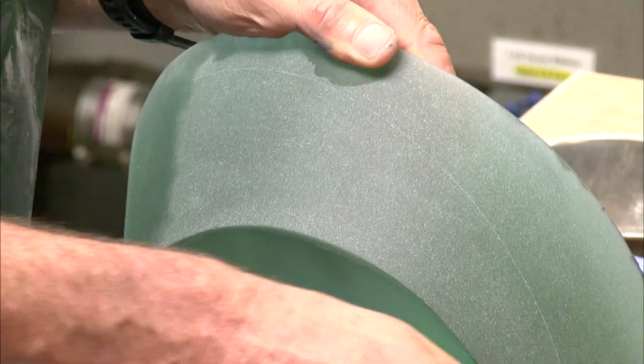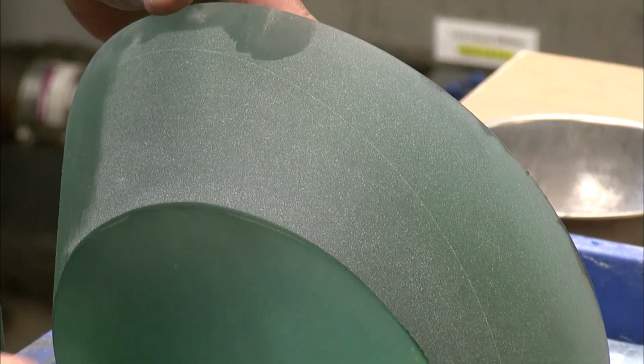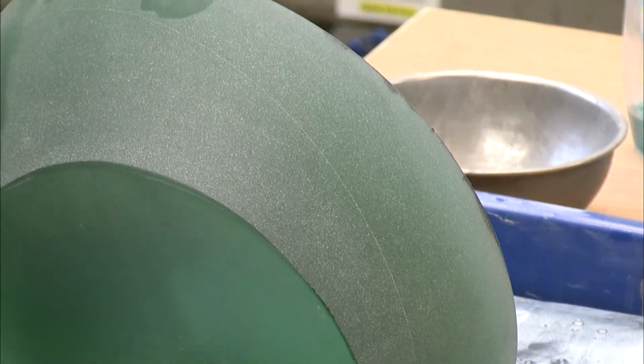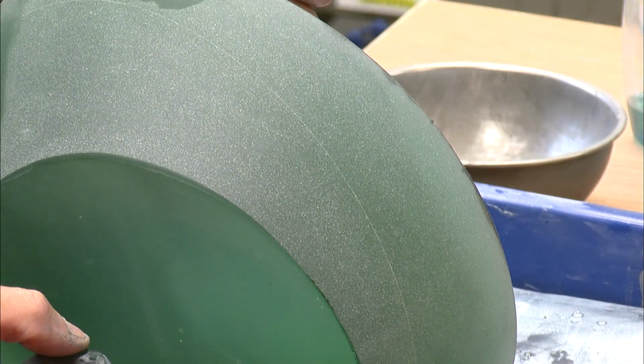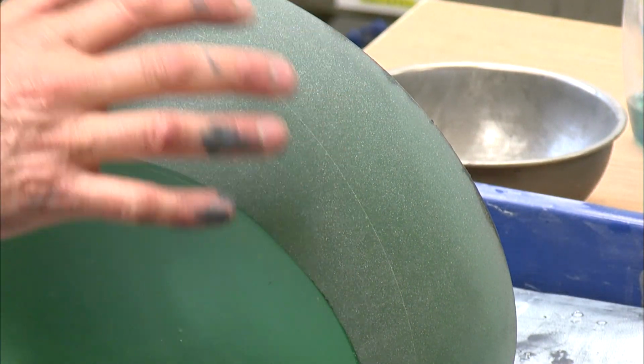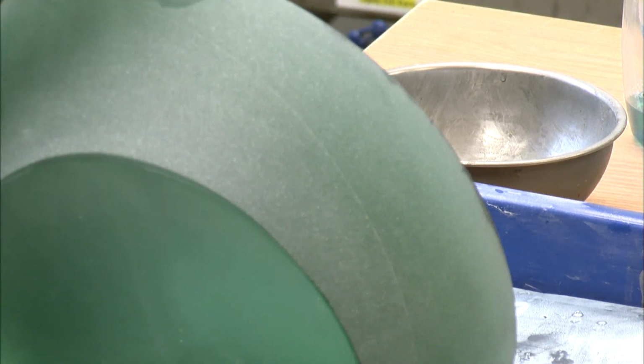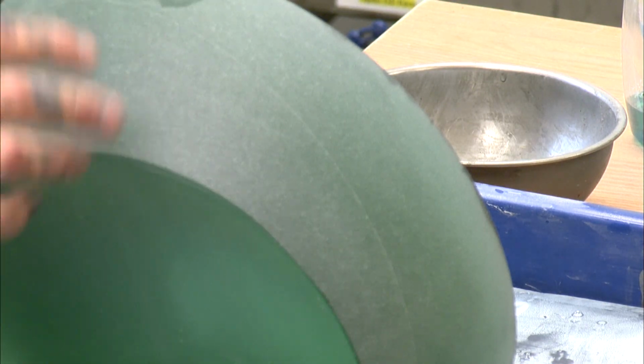We're just starting to slowly build in a little bit of the 400 grit. It needs a little bit more. There you go, that's a better shot of it. And you still see those 80 pock marks in there, but you're starting to see a matte surface come over the surface. We'll do that for a few more minutes, and then we'll take you through the last couple of steps.